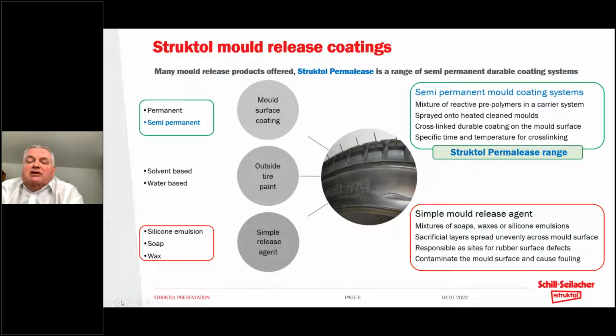So in a way, the very release agents that we use to protect the mold or to improve the release from the mold can act to contaminate the mold surface and accelerate the degree of mold fouling. On the other side, then we could see perhaps coatings that would be considered to be very permanent. So these would be processes carried out quite often offline on the mold. So things like surface coatings, perhaps chromium plating or some kind of plasma deposition technique to treat the mold almost once for its lifetime to modify the surface of the mold to prevent sticking.